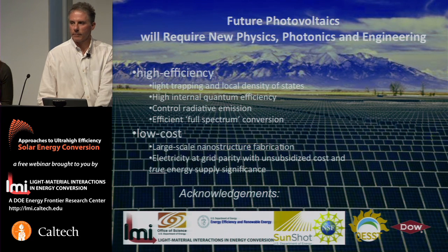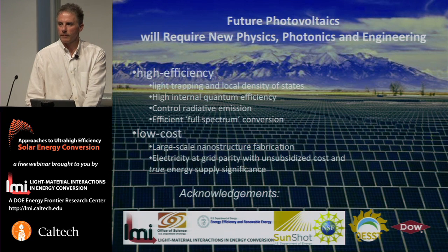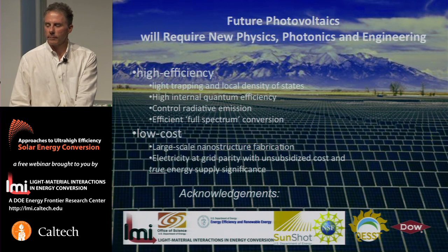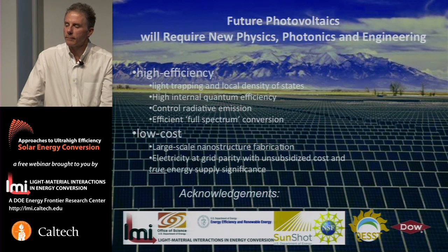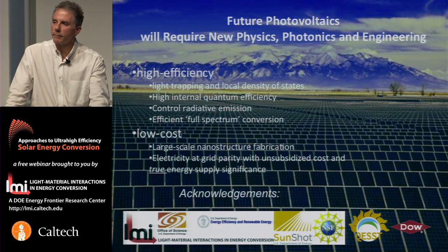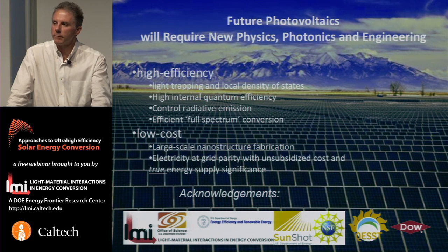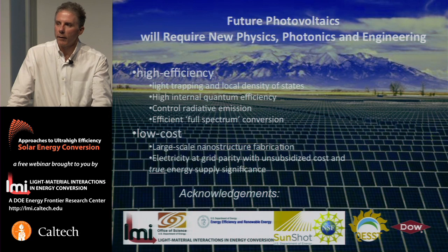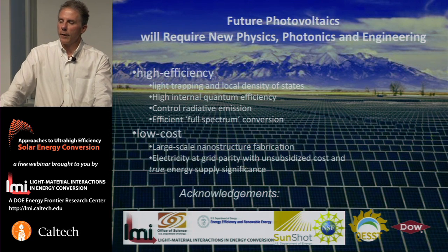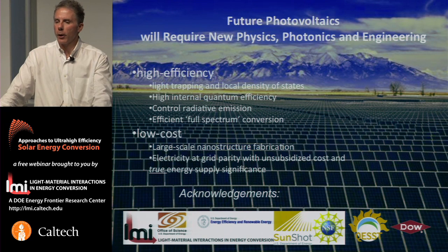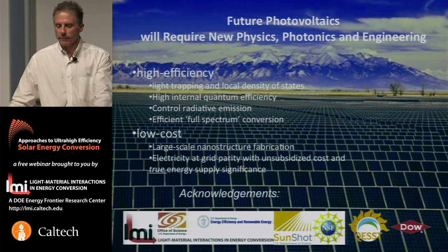The general questions online were related to the commercial viability of these complex structures: the plasmonic light trapping, narrowing the emission angle, and the spectral splitting. To take plasmonics as an example, they can increase efficiency by combining with thin film solar cells like CIGS and CZTS. But the plasmonic material itself is made from a noble metal. How could you reduce the cost of the gold or the silver structure?